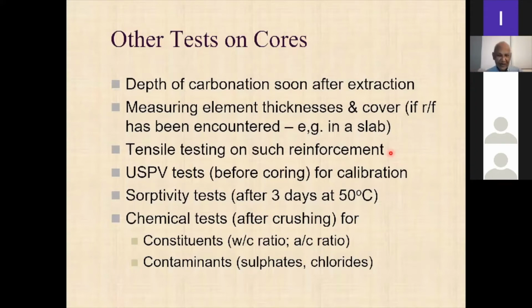Now, you should not cut any reinforcement if you are taking cores from a column or a beam. Ideally, you should not take cores from a column or a beam, right? Because in a column, you will be weakening the concrete. Like I said, concrete plays a big role in a column. And in a beam, of course, you may be able to take a core, but again, you must make sure you do not compromise the shear strength of the beam. You must try to avoid all reinforcement and take the core at the mid height of the beam and at the mid span also, because at mid span there will be almost zero shear, right? If it's uniformly loaded, of course, right?